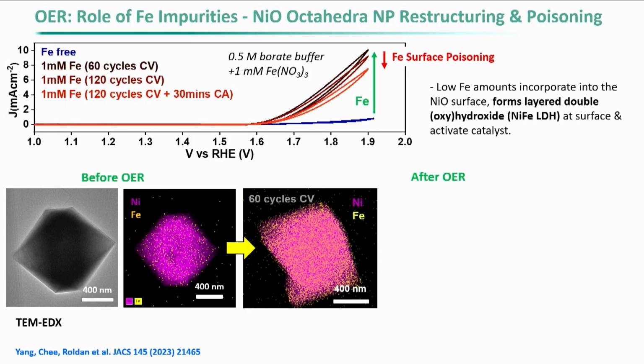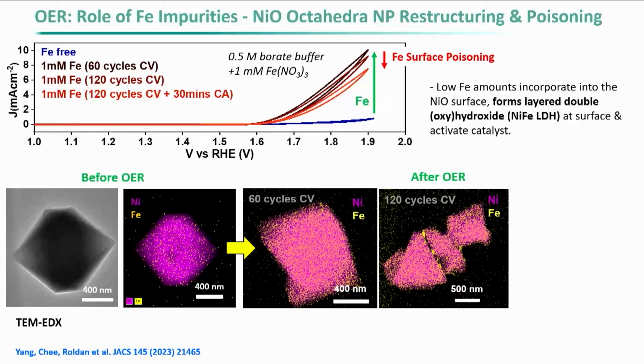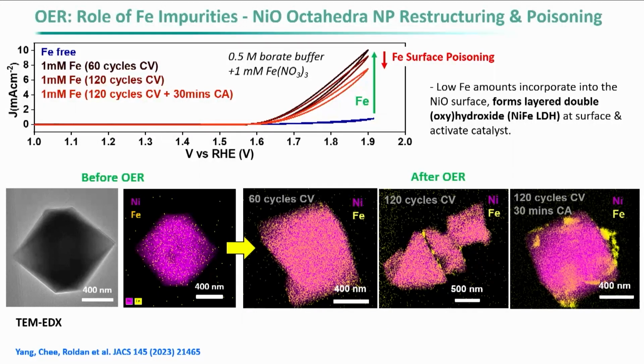After OER, if you continue running this reaction for a long time, you start seeing the formation of these clusters on the surface. So the impurities at the beginning are coming into your active surface, and it makes from this nickel oxide one of these structures, a layered double oxyhydroxide layer, just from the impurities in the electrolyte. This is good, this gives you the activation. But if you keep trying to put iron, then you start seeing that the iron doesn't go more into the bulk of this material, but it starts accumulating on the surface as iron oxides, then your catalyst is dead.